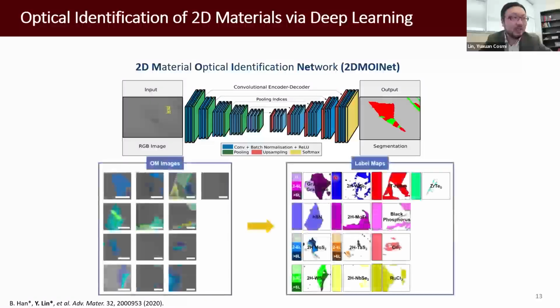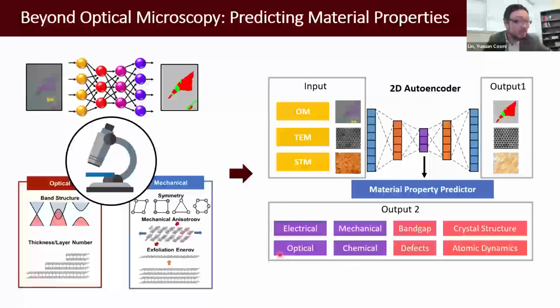We can train just one network which is able to detect 13 materials in our database. Here are the lists. We also use some examples to demonstrate that it can detect both what material it is and the thickness for each material. For the network, we just input this optical microscopic image, and it gives you this label map for the different types and also the thickness of the material. So that's basically automating the flake hunting process. But we can even go beyond that.